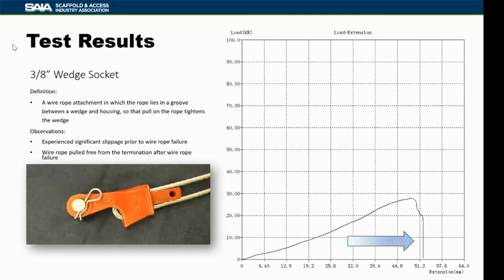The wedge socket. A lot of people said, we can't find 5/16 as readily, so we'll use a slightly oversized 3/8-inch wedge socket. What we saw was significant slippage of the wire rope through that wedge socket before it bound up and then allowed the wire rope to fail. In fact, we never actually failed the wire rope. We pulled it free from the termination, after about 2 inches of elongation. We'll see more on the test results with the 3/8-inch wedge socket a little later in the presentation.